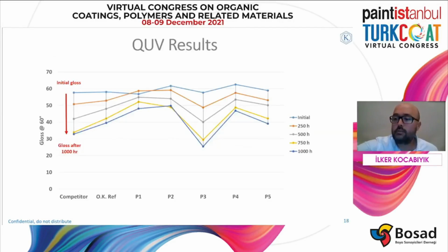All tested paints were good in terms of yellowing and crack formation. 60-degree gloss values were measured during testing. As shown in the figure, all paint samples have a starting gloss value of almost 60 gloss units initially. P4 and P5 show very similar loss in gloss as market reference polymers. Both P1 and P2 showed better gloss stability, and P3 resulted in worse performance.